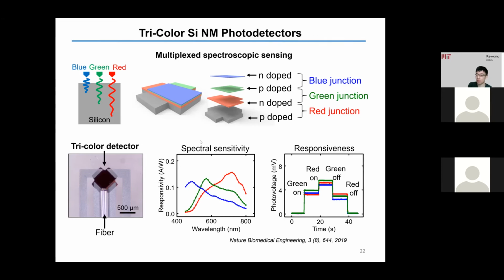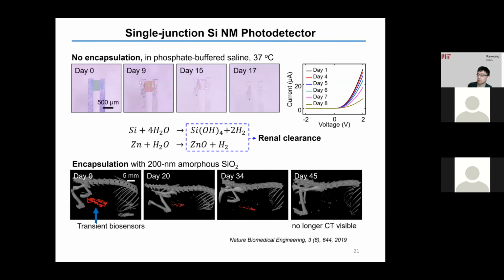The very early stage studies used silicon nanomembranes, with a thickness around 200 nanometers. Then it's feasible to observe the thickness variations when such material is immersed into an aqueous solution, or maybe the PBS solution to be more relevant to the human body. The dissolving rate is not significant. It's around maybe 10 nanometers per day or 100 nanometers per day, depending on the composition of the biofluid.